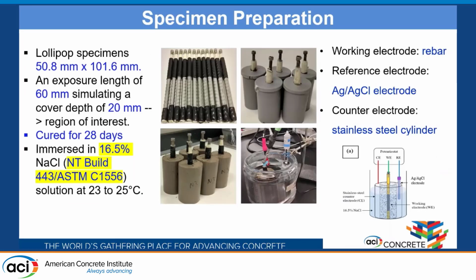So the specimen preparation procedure is a bit peculiar in this case. We have used lollipop specimens of 2 inch by 4 inch size with a centrally located rebar. This rebar is prepared in a manner that only 60 mm length is exposed for chloride interactions and the rest of it is sealed. This assembly, the lollipop specimen, is cured for 28 days, ambient curing, and then it is exposed to 16.5% NaCl solution, and thereby the corrosion testing is conducted at designated intervals.